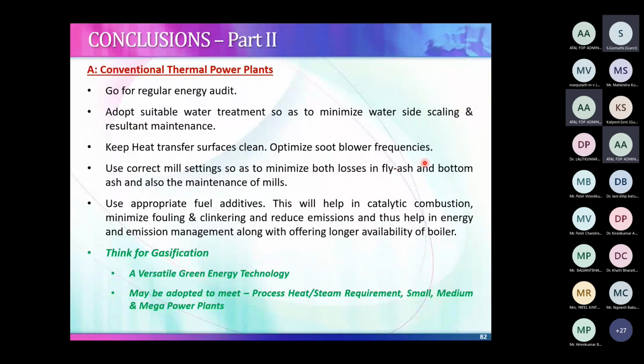And this is very important. Use correct mill settings so as to minimize unburnt losses in fly ash and bottom ash, and also the maintenance of the mills. Now this is a practical aspect. You have to go for mill setting. The distance between two bowls of the mill is very critically set so that you get the correct quality of pulverized coal, which will give you the minimum unburnt in bottom ash.